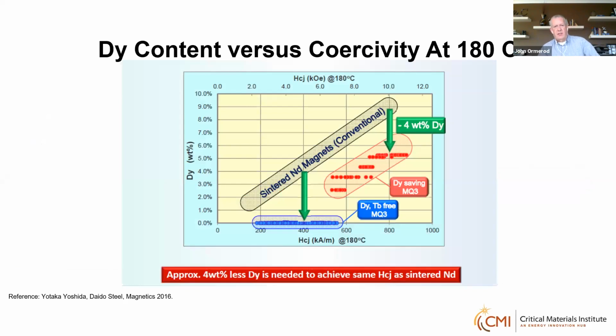Now, I think the main reason is because these magnets are starting with melt spun alloys, and so they're beginning with a much finer grain size, at least a factor of 10 less than the sintered magnets, which enhances the coercivity. In fact, if you look at this chart, it's a little hard to see, but it's telling us that if you have a motor that can tolerate, and this is at 180 degrees C, a coercivity of maybe 6 or even 7 kiloersteds without demagnetizing, you can use these hot press magnets with 0% dysprosium or terbium. Now, if you need higher coercivities, there is some dysprosium required, but what they're claiming here is it's probably around 4 weight percent less than in the conventional sintered magnet.